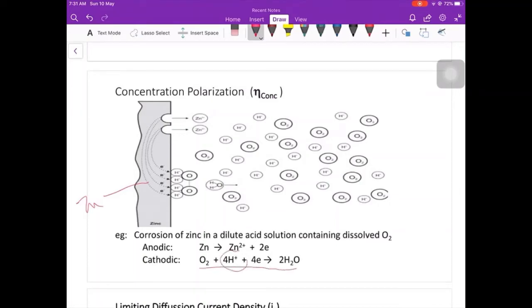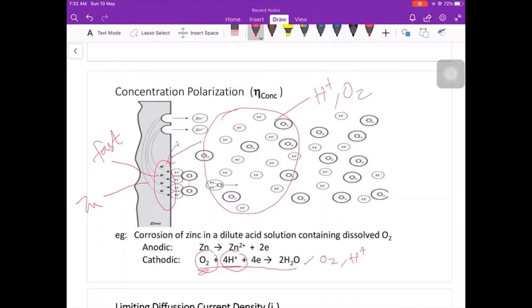Okay, so look at this. For example, zinc. This is zinc metal immersed in an acidic solution that contains dissolved oxygen. Since there is low H plus and low dissolved oxygen, the controlling factor will be the movement of O2 as well as H plus to the surface. So electron transfer is fast, so that is not the controlling factor. The controlling factor is how H plus and O2 move to the surface.